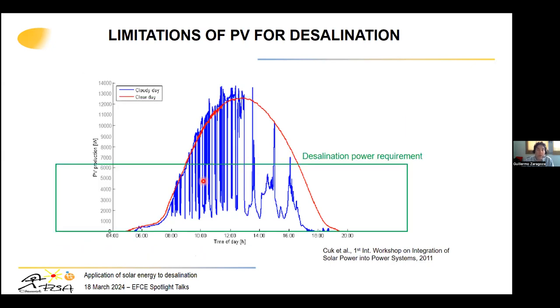One solution can be to increase the size of the PV field. Like in this case, the peak is much larger than the power demand, the peak of the demand. And then you can guarantee that at least during this time, you are covering the required power. So by having excess PV capacity installed, you can supply, I don't know, what is this, 4 or 5 hours, enough power for the desalination in a stationary and constant way. But then all this excess energy produced during this time is lost, unless you store it. And that's what is done when you over-dimension the PV field to have enough power during a certain time, then all this excess energy is stored and used before and after.